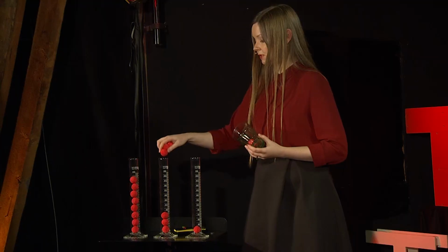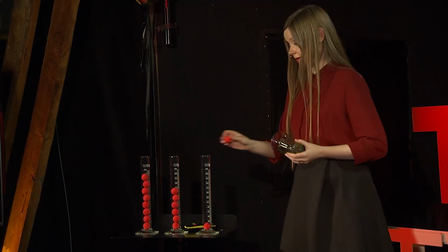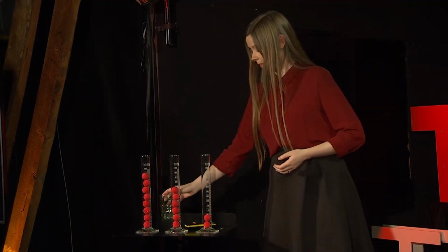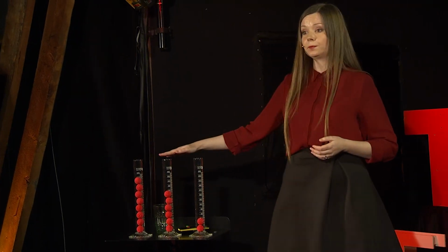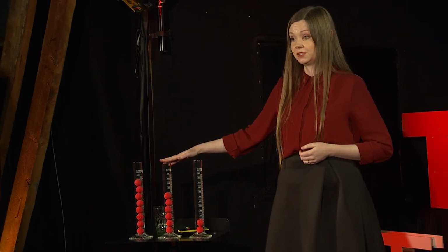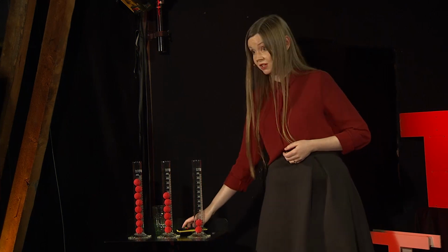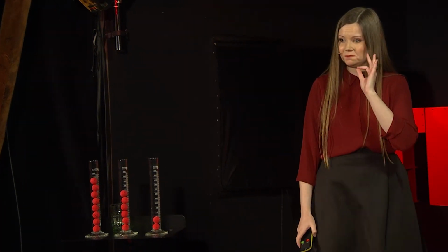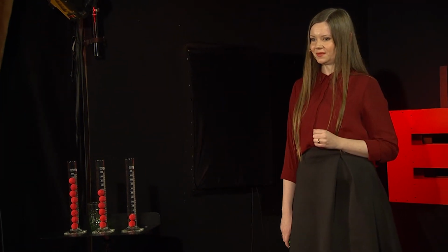After doping the material, we test it again. And we see that we increase the amount of oxygen that can be inside it at room temperature, medium temperatures, and higher temperatures. These oxygen here are the key to making these membranes a reality. And now we have enough of them to make the membrane be at its best performance.